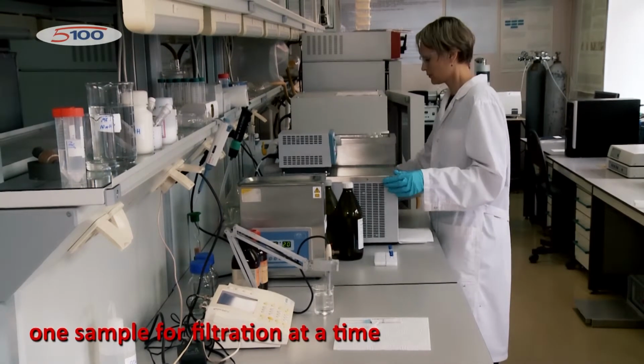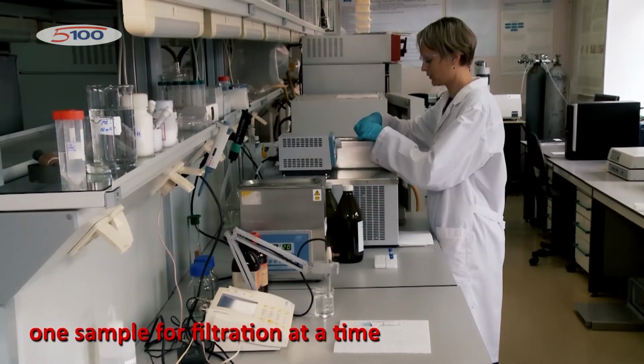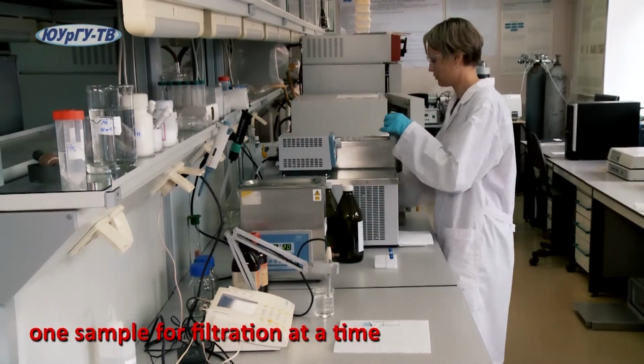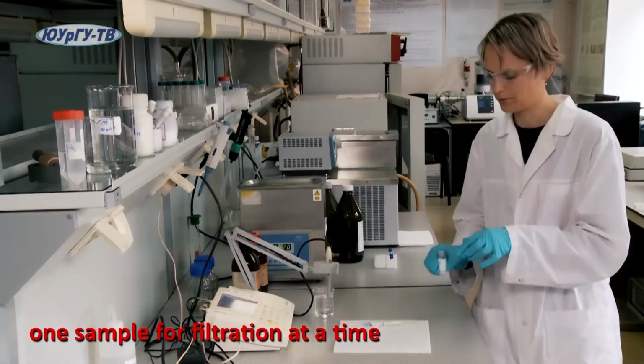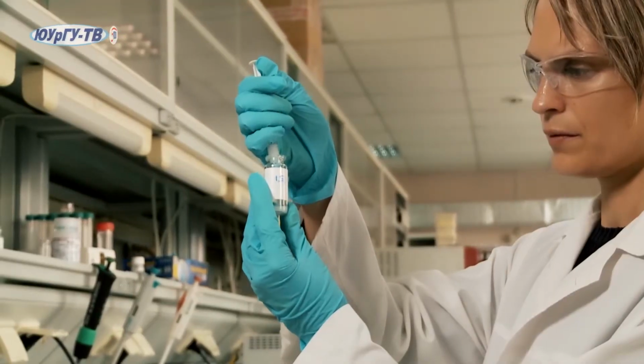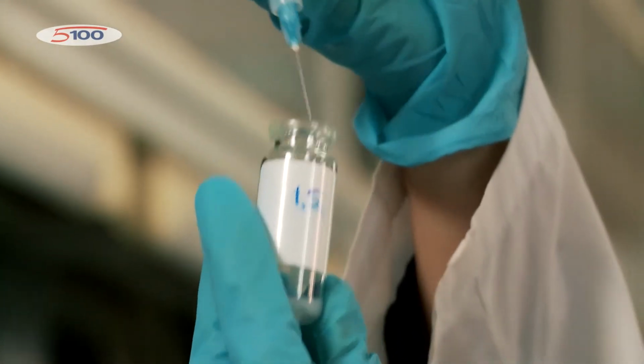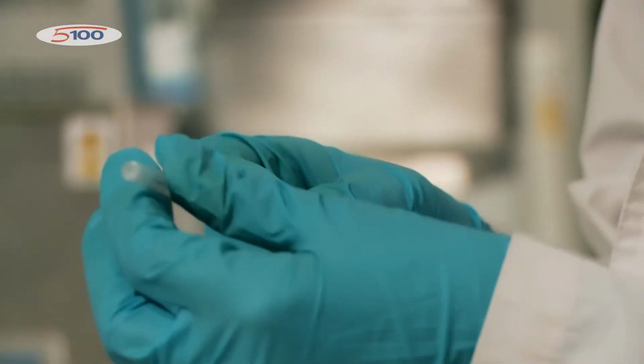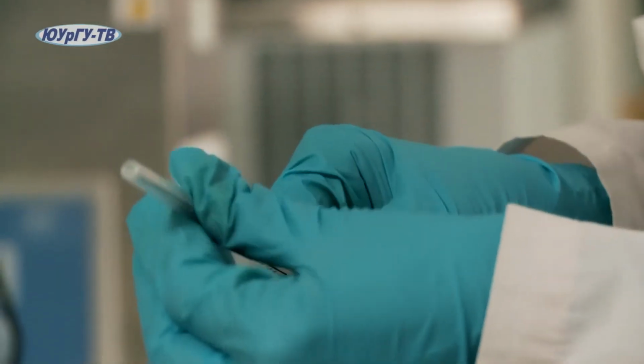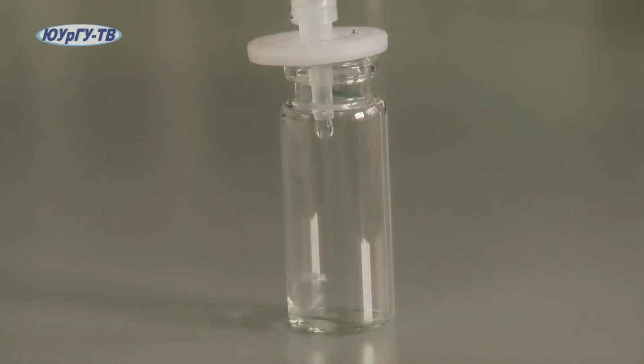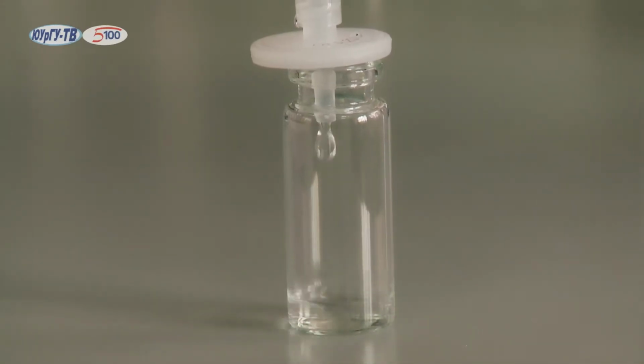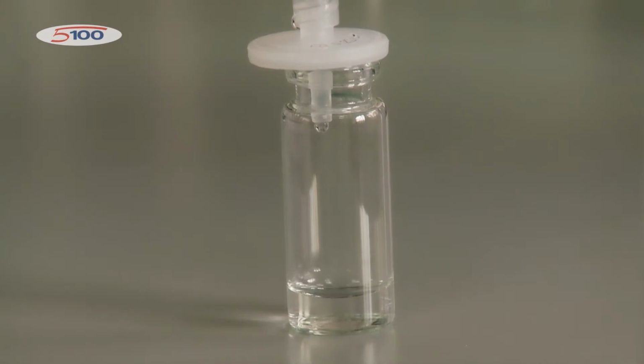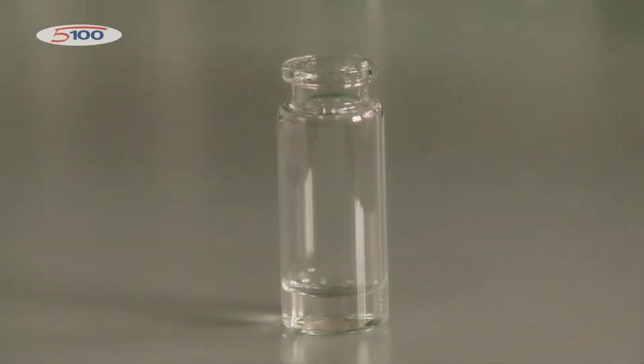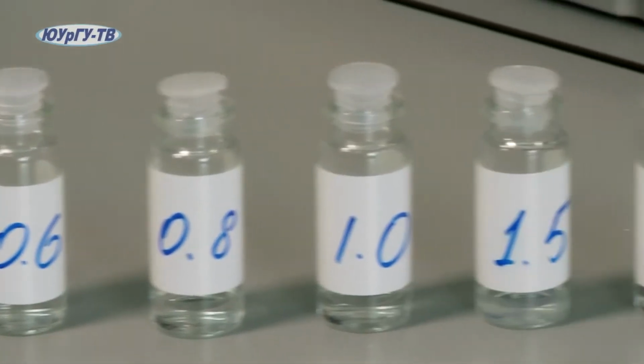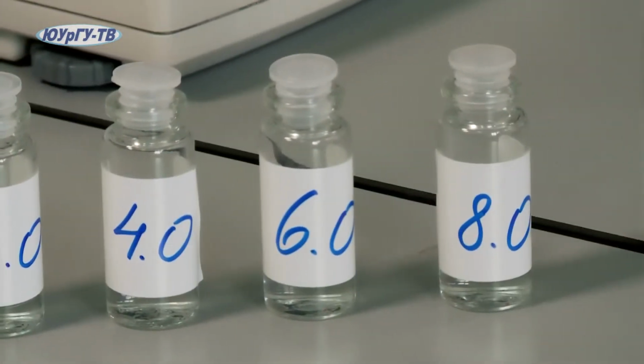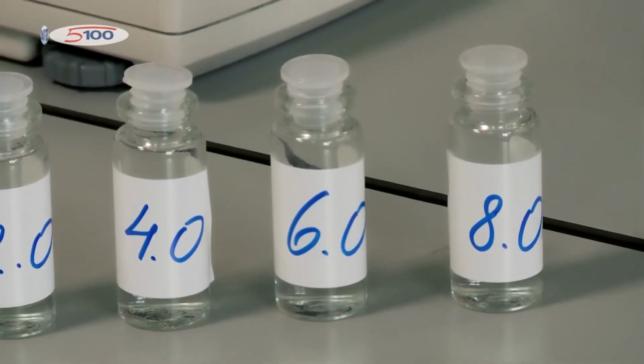In order to avoid temperature-induced re-equilibration, take out one sample from the thermostat for filtration at a time. Take a sample of the dipeptide solution from each glass vial with a syringe. Remove the needle from the syringe and put on the syringe filter to filter the dipeptide solution into the glass vial. Repeat with samples of other concentrations. Now these samples are ready for analysis.